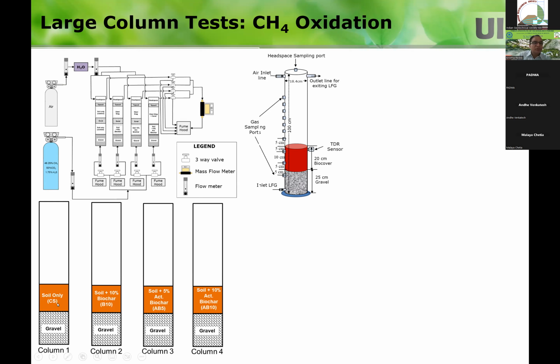In one of them, we put only soil. Another one is 10% biochar. This one is 5% activated biochar. Here is 10% activated biochar. We were trying to look at how much is the optimum biochar amount and whether we should use activated or not activated. So that's the idea for designing these experiments. Basically, we have a distribution layer and this is the soil layer. And then later on we're going to put the slag on the top of it. But initially, we wanted to look at this biochar amended soil in this type of configuration.